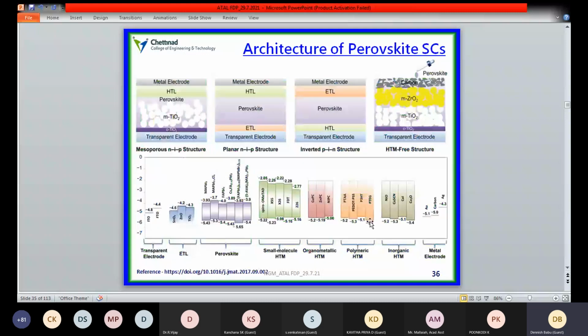As mentioned earlier, these are the various architectures of the perovskite solar cells. So, mesoporous titanium dioxide, which is used as an electron transporting layer, and the planar n-i-p junction structure, and the inverted p-i-n junction structure, and the hole transporting material free structure also. So in this structure, some kind of zirconium oxide based material and mesoporous titanium dioxide based material will act like N-type and P-type structures.